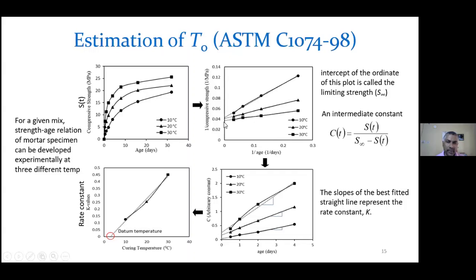We can make a best fit straight line, and these best fit straight lines are going to cut the ordinate at different points. If we take the inverse of them, we get some strength values in terms of megapascal, and these strength values are denoted as S infinite. So very simple. In the laboratory you can develop that and find out this S infinite for 3.